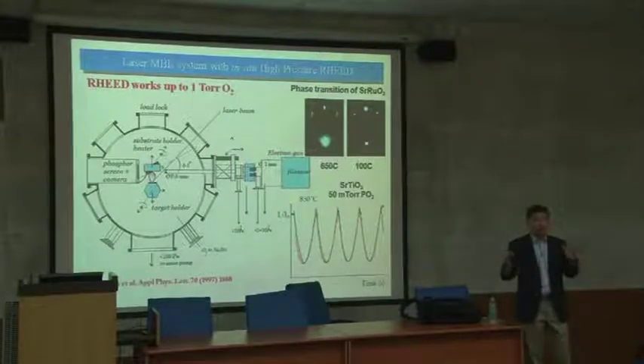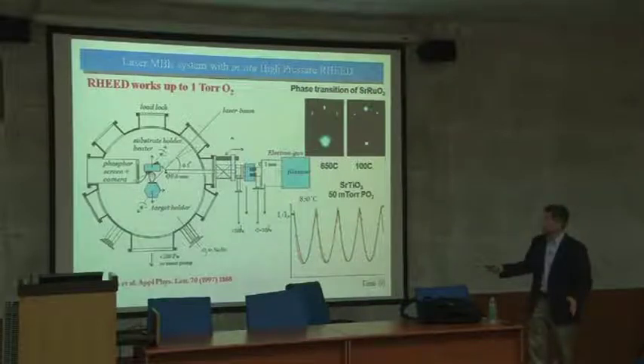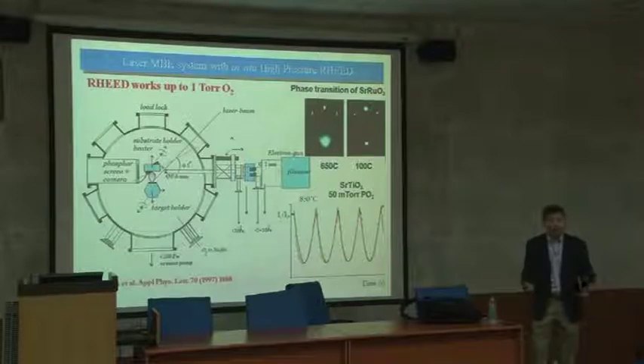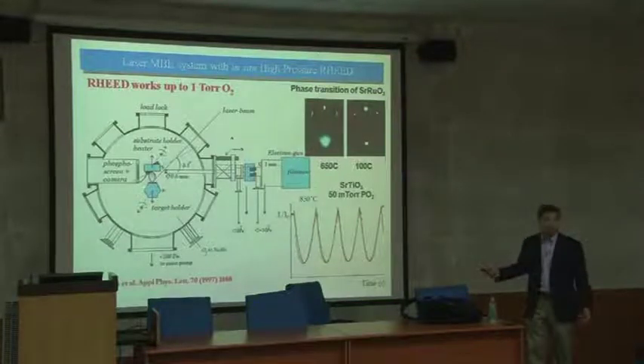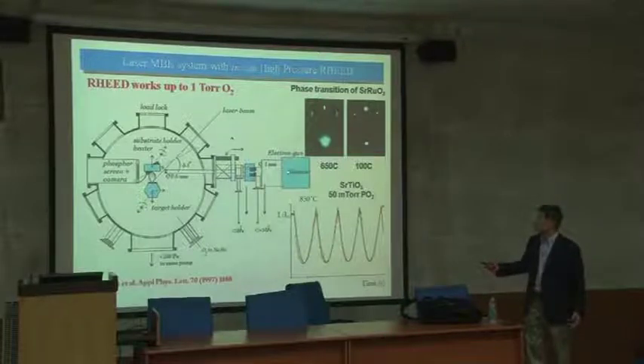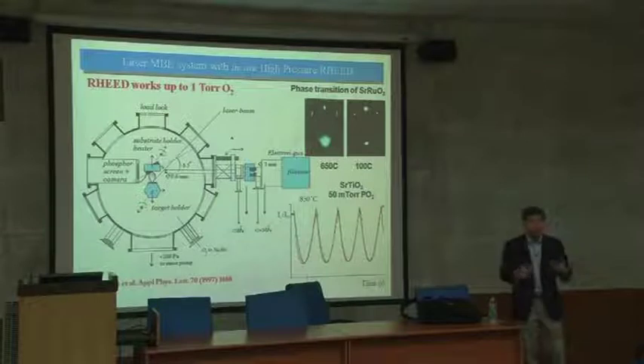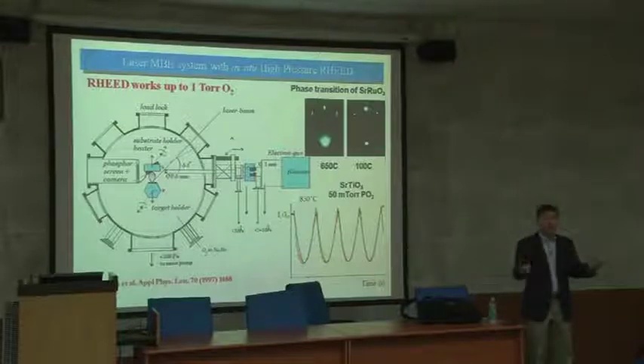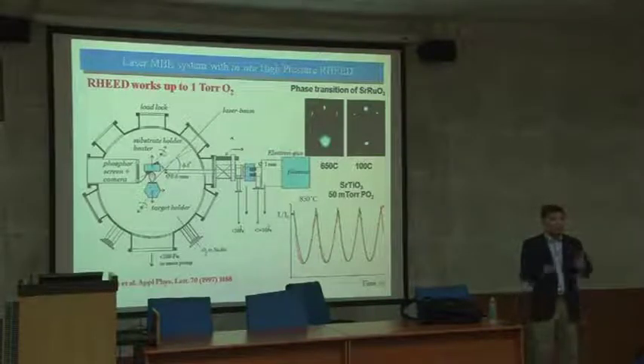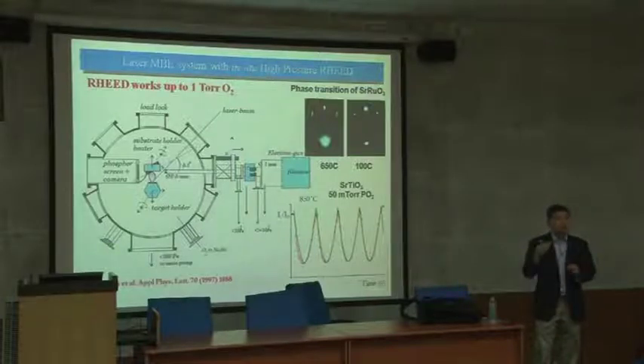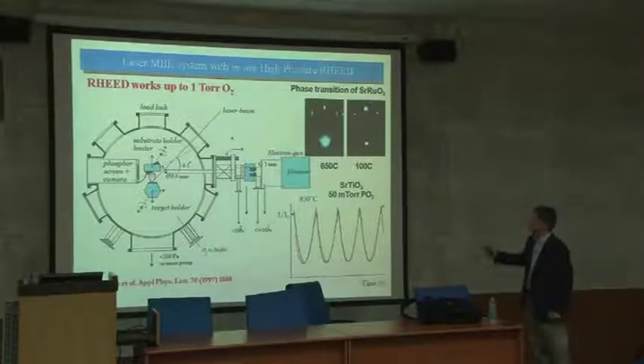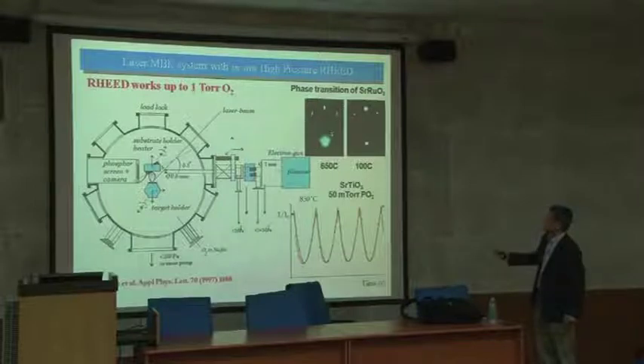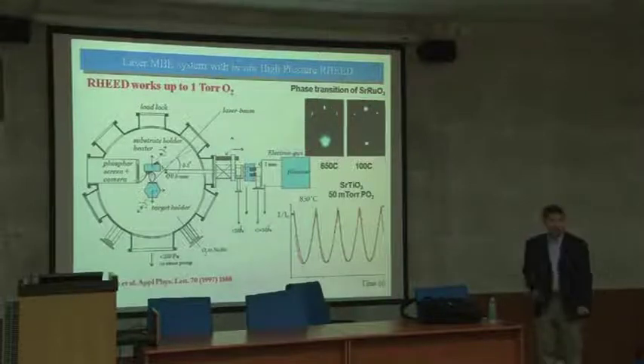You need a large differential pumping ratio because you have very tiny holes, and the additional two-stage pumping makes this region a good vacuum. So that means the electron beam travels from here to the exit of the beam inside the good vacuum. So your mean free path is very long, and you can travel without scattering. You can exit here, then the sample is very close, and you can see that. So that's one very important step to make this atomic layer control, in situ monitoring possible. And then you can see a diffraction pattern. It's done at very high pressure. You can see a beautiful pattern.